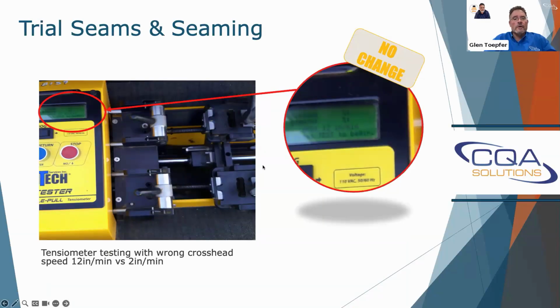Testing with the wrong crosshead speed. In this case, it was supposed to be 2 inches per minute for HDPE, and they were running it at 12. And I'm not even sure what the 12 is, maybe PVC or something. I don't know offhand what the 12 is, but I think it's usually 20 for LL. But anyway, that aside, it was wrong. A lot of people don't catch it and it'll impact your values. And if it impacts your values in the field, then you could end up with failed seams because your values were skewed.